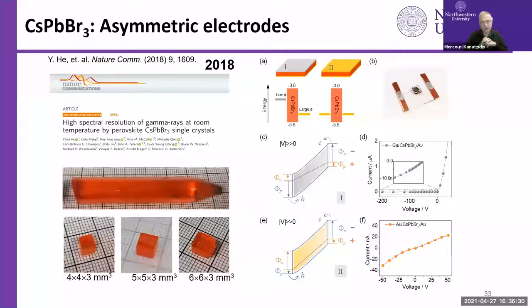So then we put electrodes on this material to try to make detectors. And so first we did what we always did, put gold on both sides of the crystal. We obtained this IV curve, which gives us about, say at minus 50, about minus 30 nanoamps. And then it goes down. If you go to minus 100, it goes way down. So by the time you get to 100 volts, 200 volts, or 300 volts applied, you get a very high dark current. We believe anything above 100 nanoamps is very high. And this detector that has gold on both sides did not work, did not give us any response.